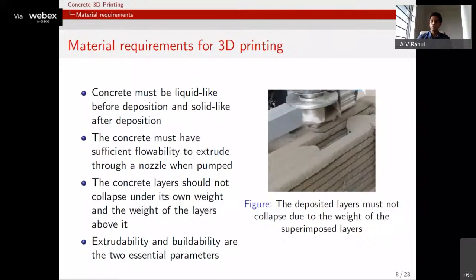But once it's come out from the nozzle, the concrete should undergo a transition to a solid-like behavior. In polymer printing, they do this transition based on temperature. Once the polymer comes out, it's quickly cooled. Inside the pump and the regions where it's being transported, it's heated above its melting point, so it's like a liquid. Once it exits the nozzle, the sudden transition in temperature causes it to transform quickly to a solid. In concrete, we work in a different way, which I'll talk about in the coming slides.